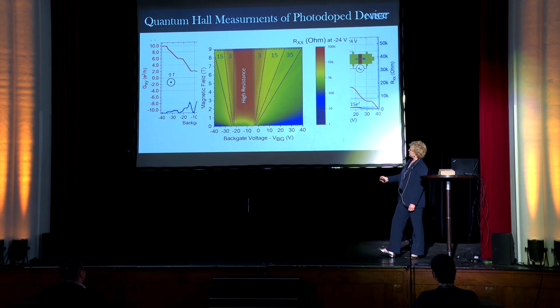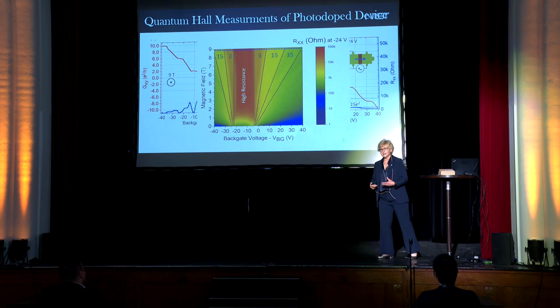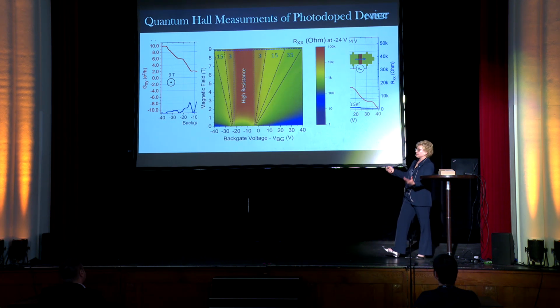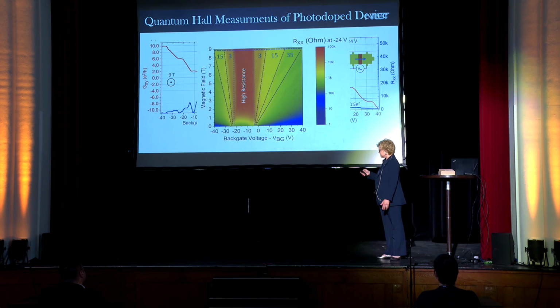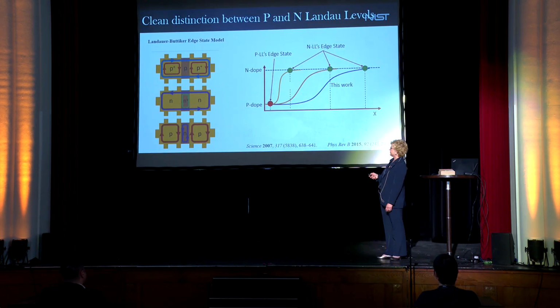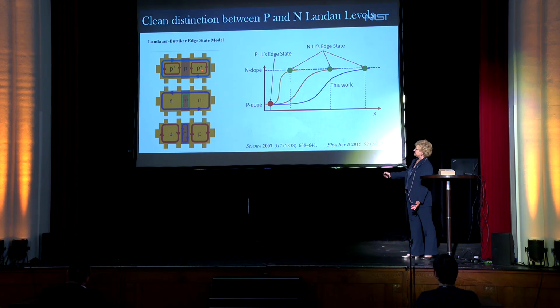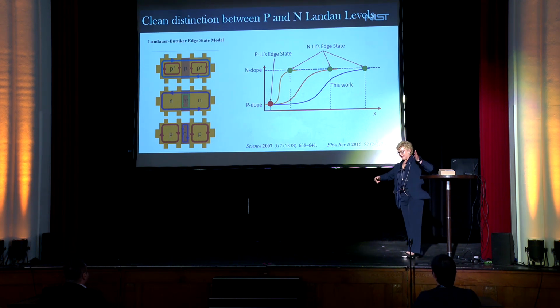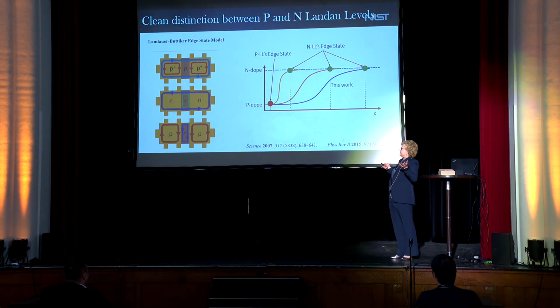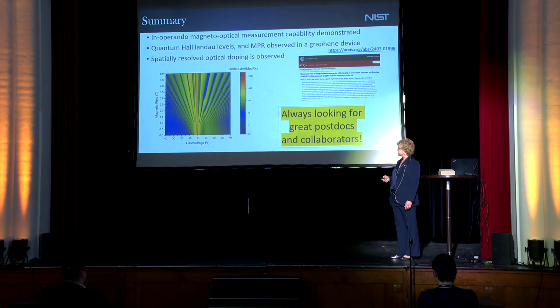Here is, again, a fan diagram. What's interesting, in the PNP region, we have very high resistance. So it's an insulated area. And so it is surprising, but that is kind of where we are in this sort of new science area of the electrical. And then just using a very typical edge model, we're able really to explain the data that we're seeing and the different Landau levels that we're measuring. So again, we're able to separate the P and the N quite physically and cleanly. And so it's exciting. Again, we're very new to electrical, so we're still figuring things out.